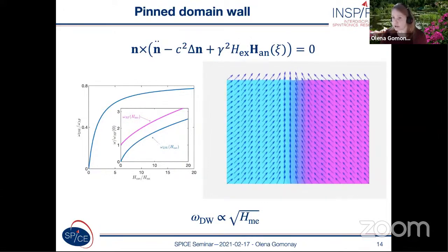And it has non-zero frequency, whose value scales with the value of magnetoelastic interactions. Such pinning of the domain wall is a result of the inhomogeneity which is induced by the spontaneous strains into the sample. Interestingly, the frequency of the domain wall in this case, of course, grows with the value of the magnetoelastic constant, as shown in the left panel, but it is always below the continuum, below the frequency of the antiferromagnetic resonance.